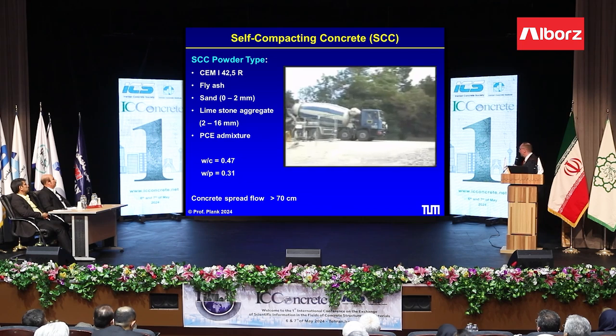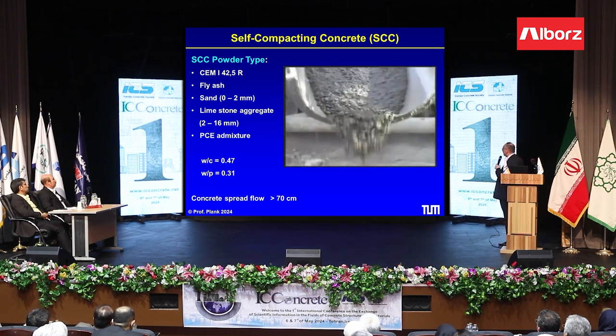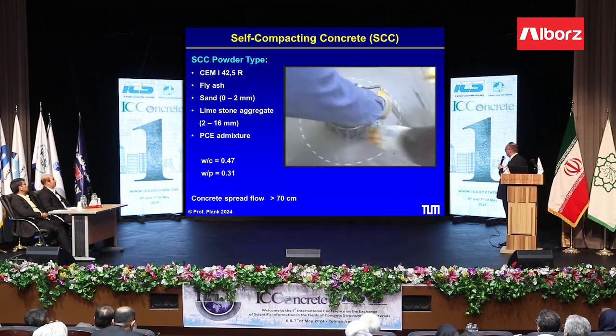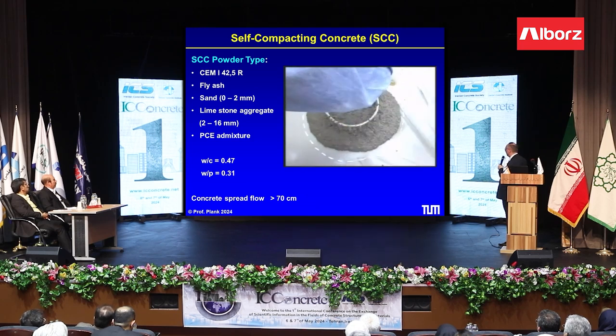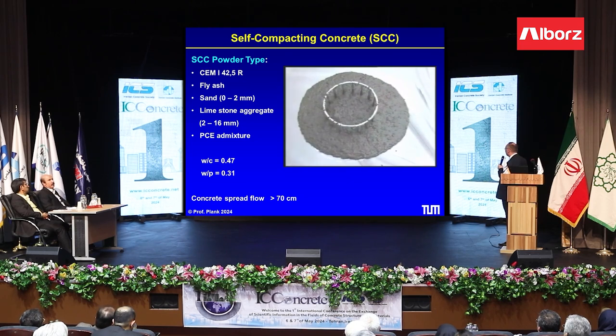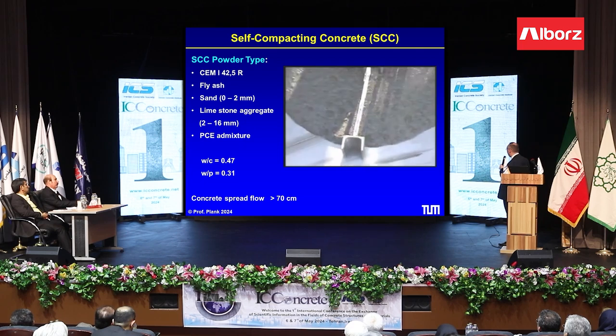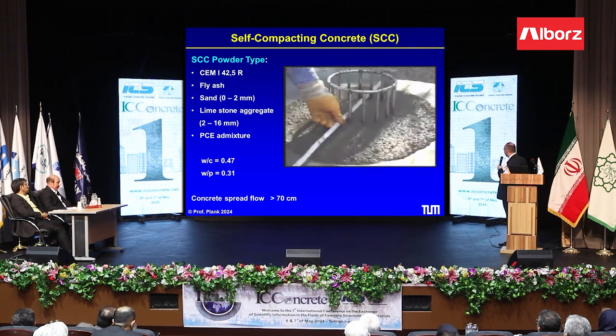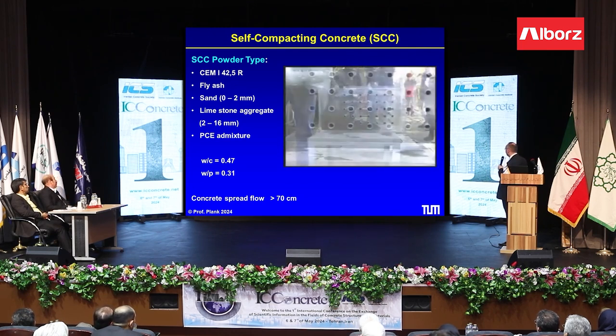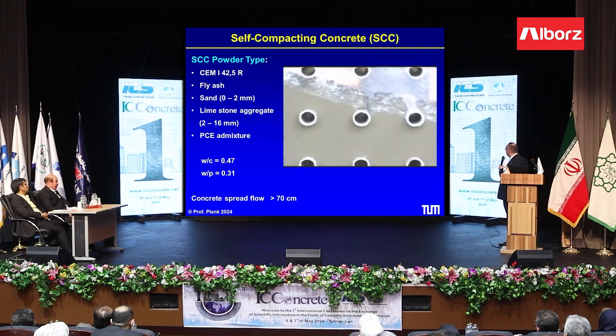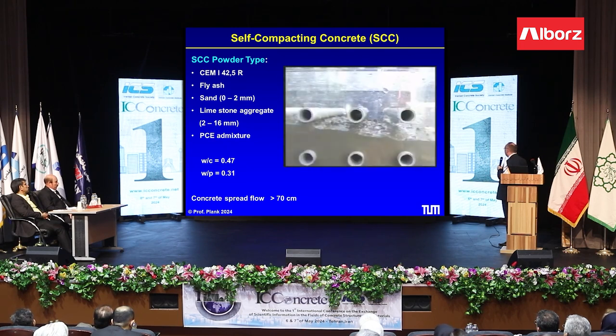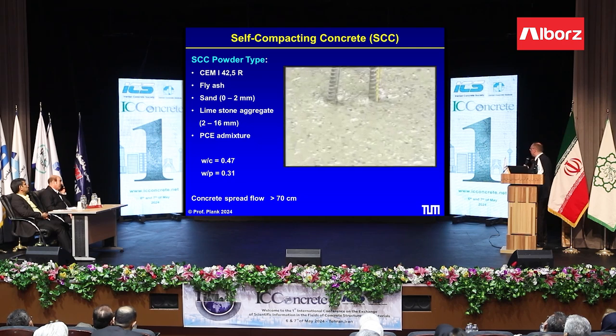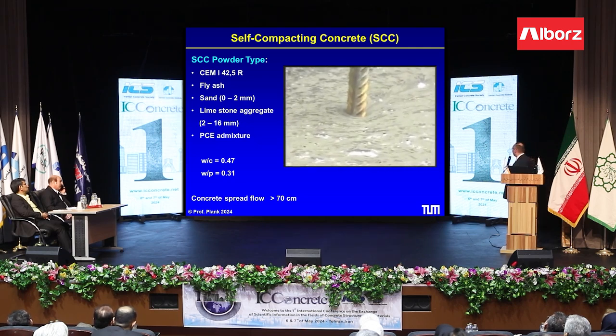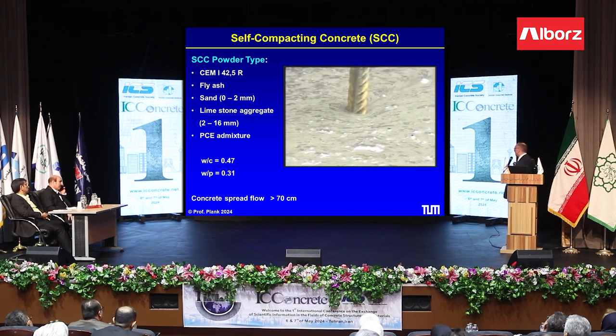And let me show just a short video of SCC. We call it a powder type based on cement, fly ash, sand, limestone, aggregate, and a polycarboxylate admixture. This is the J-ring test. You see it has very good flow behavior, no segregation behind the steel bar here. This is the L-box test, and you see no voids, no empty space around these pipes. This is a perfect self-compacting concrete, and here you see how it releases the air itself. So SCC doesn't require much compaction. It is self-de-airing. And this is possible with advanced admixtures.